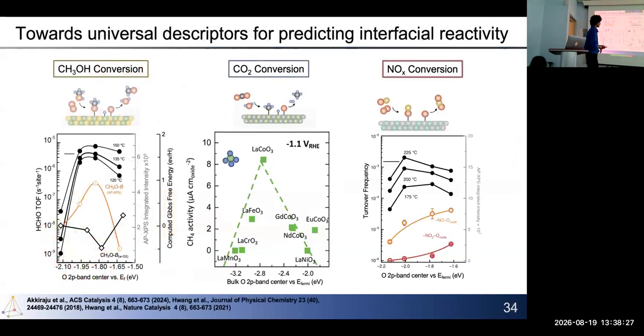Generally speaking, you can extend this approach to a whole bunch of different molecules and reactions. For example, we looked at methanol conversion, CO2 conversion back into methane electrochemically, and NOx conversion for automotive catalysts. The idea is that regardless of what reaction system you choose, one could develop these simple descriptors that help explain the trends you see for macroscopic performance.